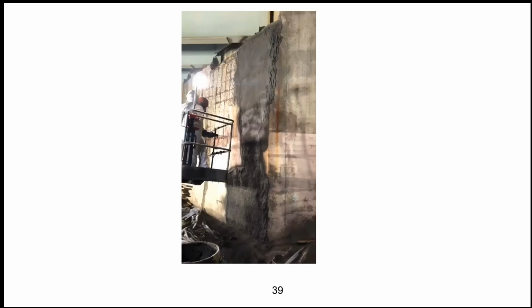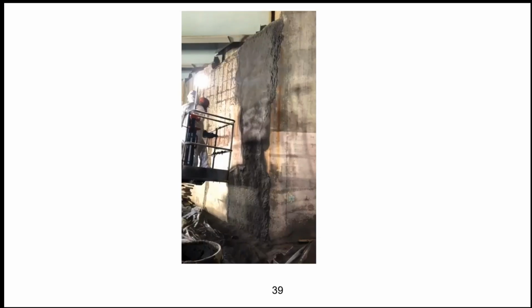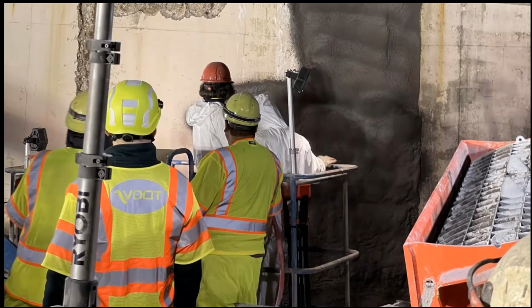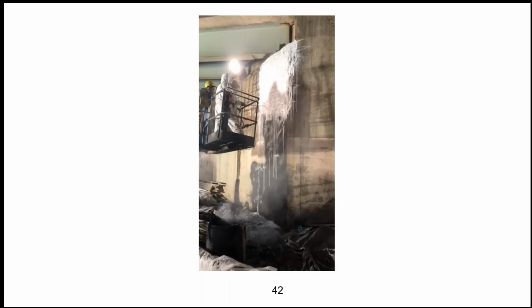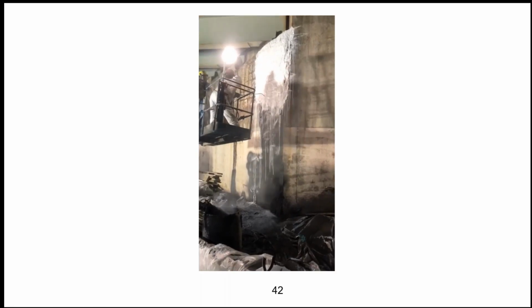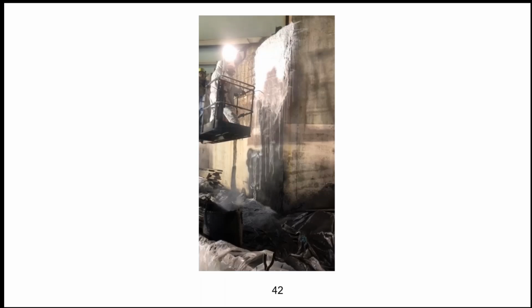And finally this is another shot. And finally we applied this curing compound. It's a white pigmented curing compound that we applied. Now we were super conservative with respect to curing. We applied the curing compound, we put the wet burlap and the plastic sheet. You don't need to do that, but we decided to do that just to prevent potential cracking and so on.